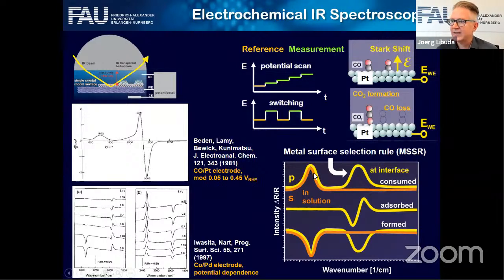One thing that is important with infrared spectroscopy is that you can change the polarization, such that the electric field is parallel to the surface or perpendicular to the surface. Now, if you're working on a metal surface, you have no parallel electric field directly at the metal surface. That means that the species that are adsorbed directly at the metal surface will not be visible in the p-polarized light. Well, so that's how you can differentiate between species that are in solution and in the electrolyte. I should have said s-polarized. So let me explain again.